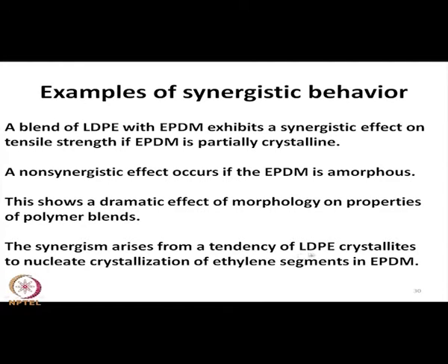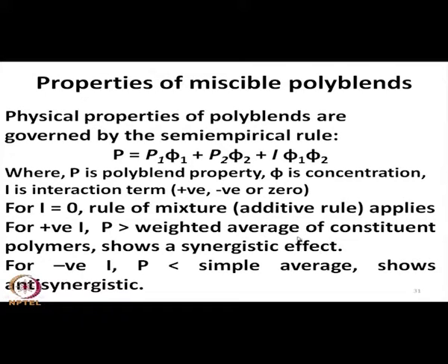This is a very interesting observation that since LDPE is crystalline, that LDPE crystallite will induce or nucleate some crystallization in the ethylene segments of the EPDM polymer. That is why the synergistic effect is available. Now, the properties of miscible polyblends can also be explained in another way.